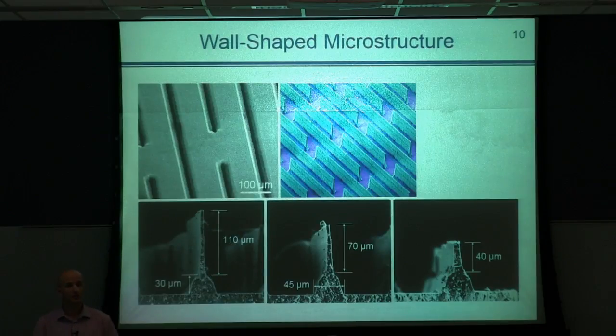Now, these are examples of wall-shaped microstructures that were created recently. So this is what we have now. An example of an image of a tungsten template that is laser machined to have structures that are used as a template in curing the polymer. This is an image of the projections that were created from polyvinyl siloxane cast against this template, and these are SEM images of the wall-shaped projections having different heights.